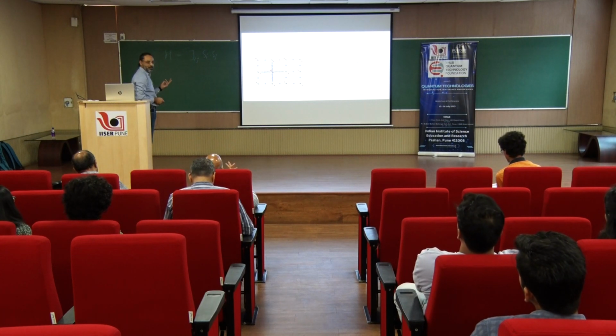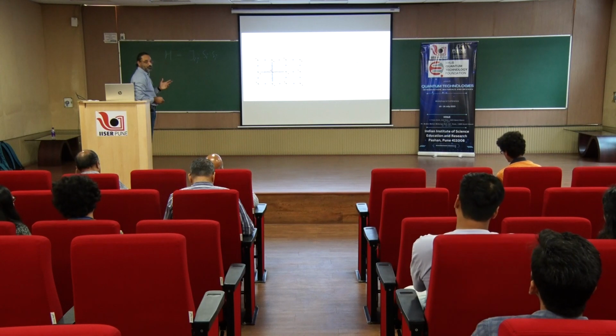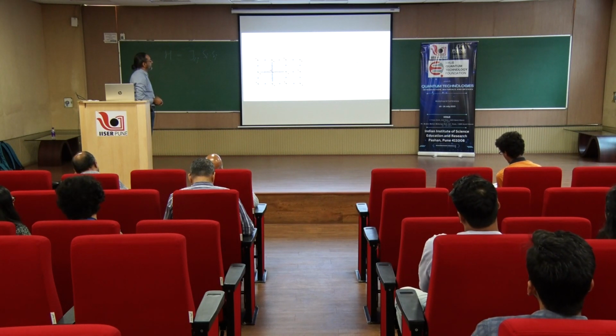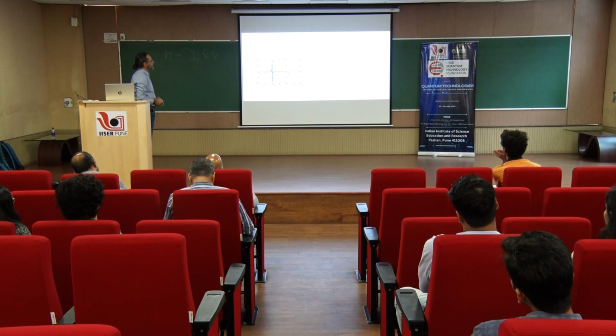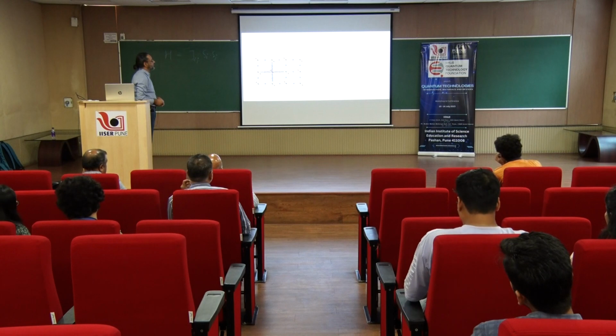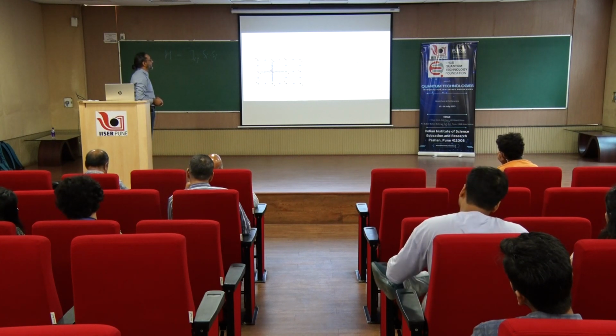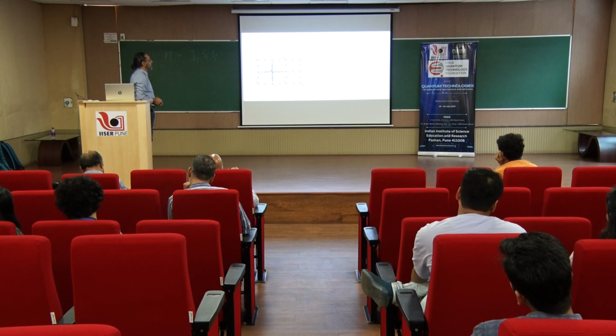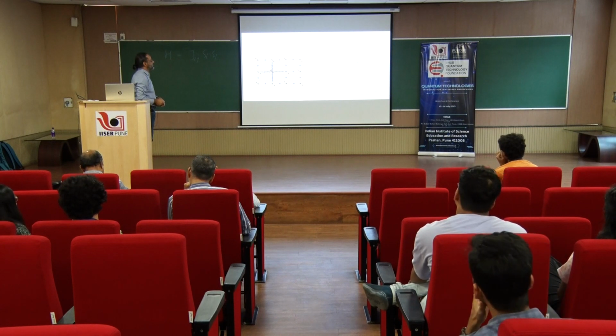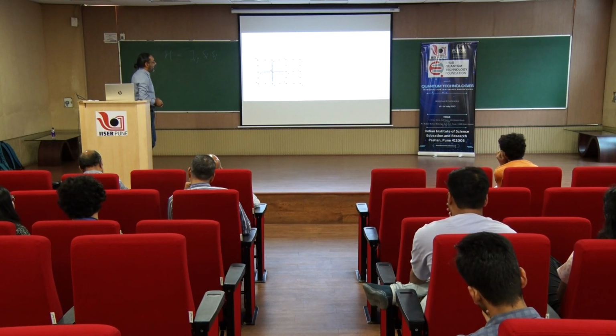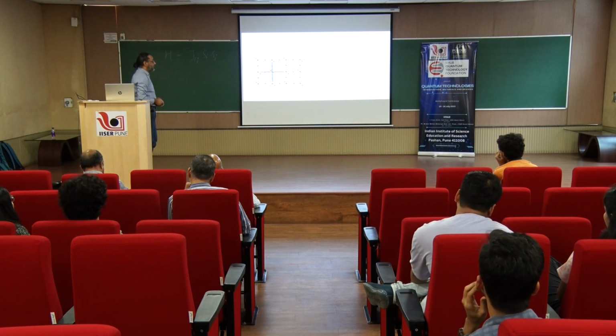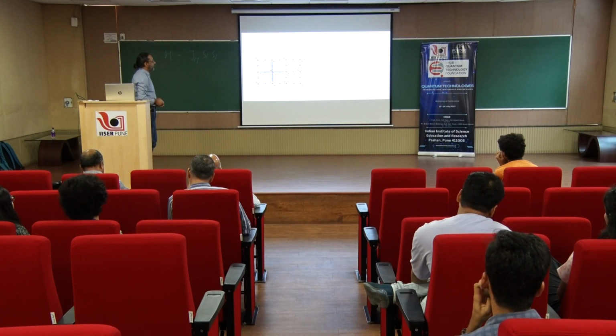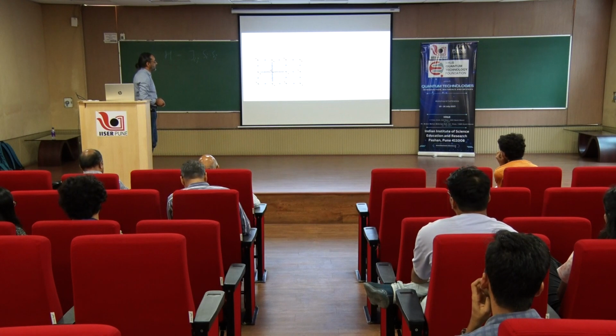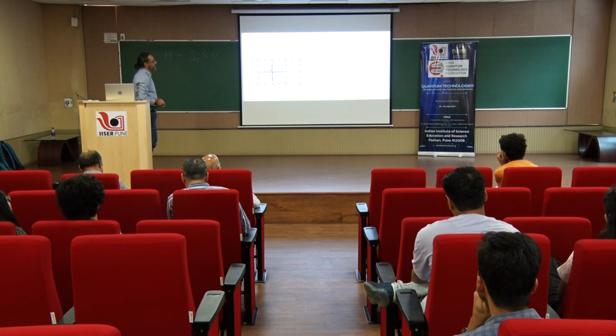Oxygen has two electrons in the p orbital. So one can go here, and after that, once this electron has moved here, you cannot have hopping of this electron either from here to here or hopping of this copper electron from here to here. This is not allowed, because you cannot have more than 2 electrons per site. So therefore the excited state here is not as low in energy as in the case of antiferromagnetic alignment. Why? Because in that case, if the electron hops from oxygen to copper like this, then this hopping channel is still open. So therefore the system can lower its energy.